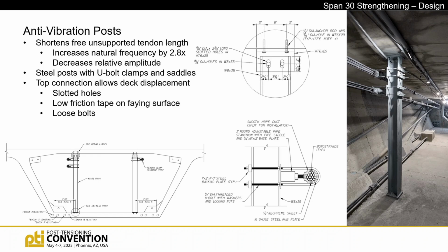And then the particular detail that's important here: we're essentially connecting the bottom slab to the top slab. That's a lightly reinforced top slab and a lightly reinforced bottom slab. Very flexible top slab, though. We did not want to damage the top slab. We were concerned about punching a hole through it. So the top connection there moves vertically. It has slotted holes, we used a low friction tape on the faying surface, and the bolts are left in there loose. So if you put your finger on it, it moves up and down, but it's restrained transversely and longitudinally.